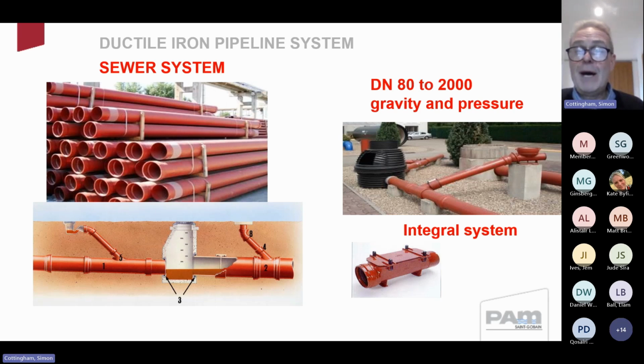The difference between clean and dirty water is that it's the same pipe. The difference is predominantly in the internal linings. A clean water pipe is blast furnace slag cement lined, typically for potability and compliance with DWI regulations, and sewer pipes have a calcium aluminate cement lining on them, meaning they're more suitable to a wide range of aggressive effluents. You can directional drill with both clean water and dirty water pipes. It's exactly the same pipe with the different linings that you would use for all applications, including the no-dig.